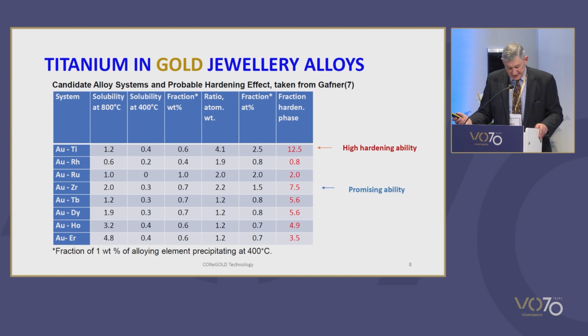The last column makes clear the reason for developing the 990 gold titanium alloy. The promise of the rare earths and zirconium are also noted. In the case of 990 gold, the precipitates are the gold 4 titanium intermetallic phase.